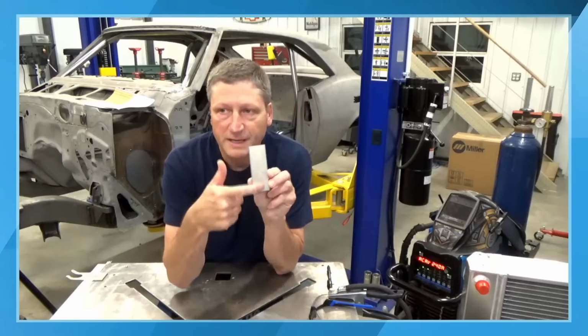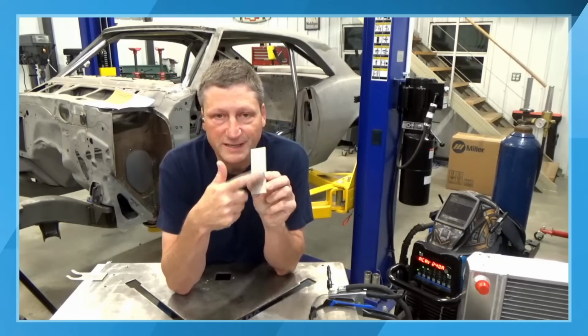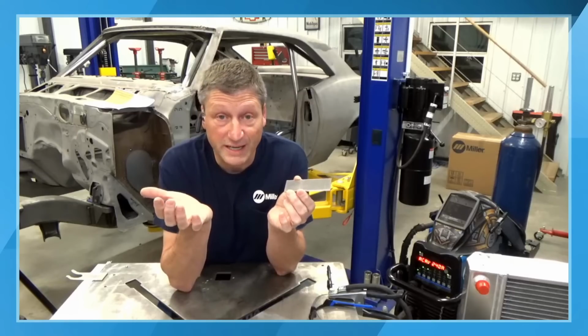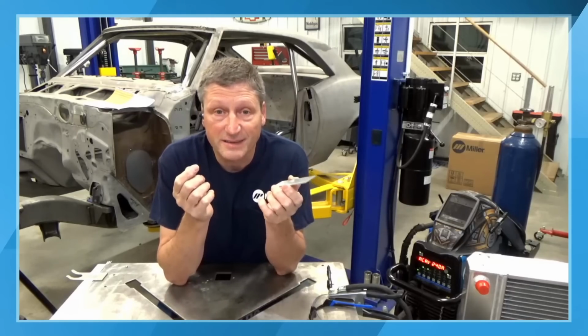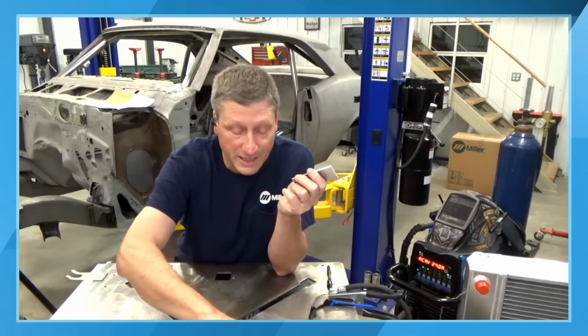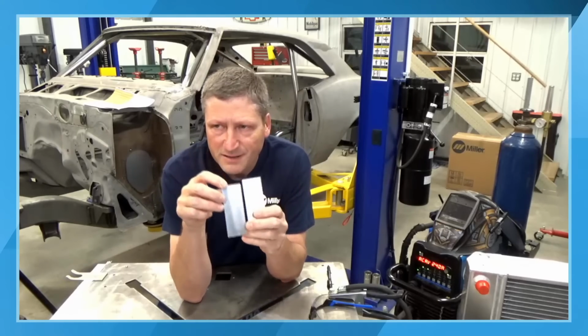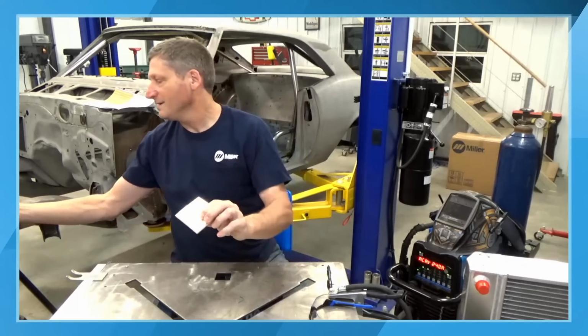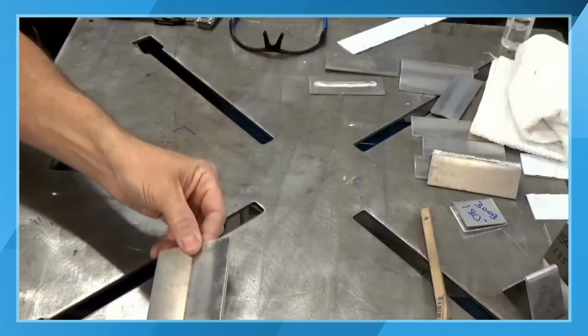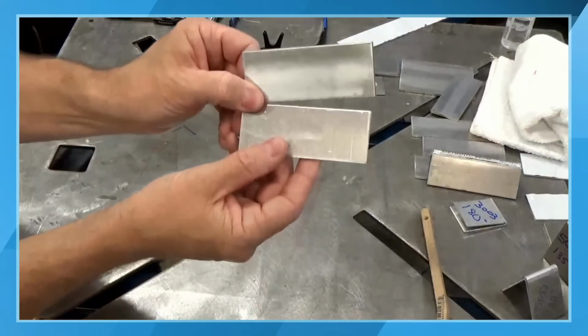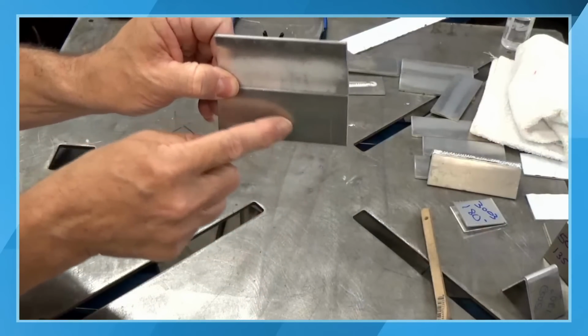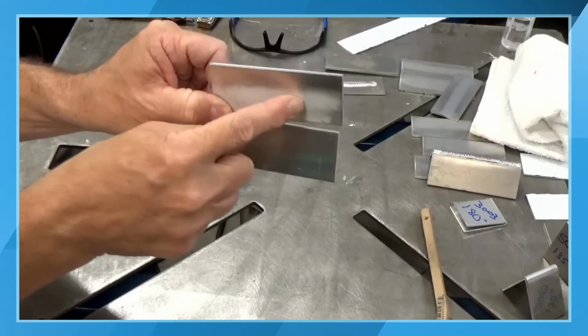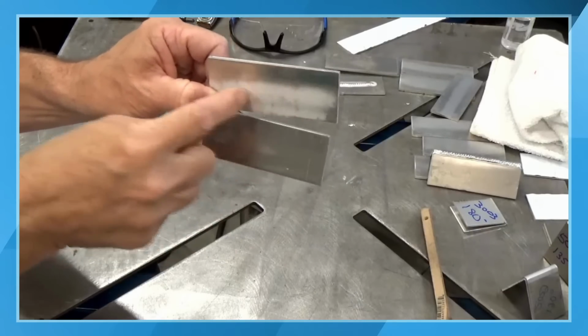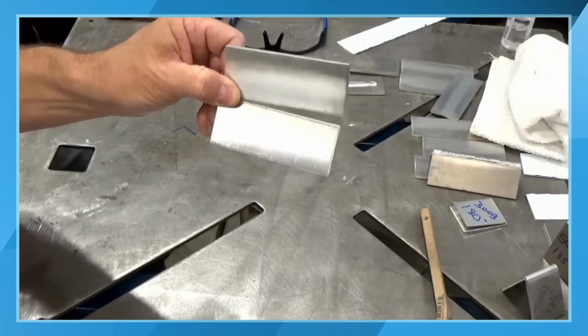So aluminum, it's nice and shiny. Well, what you're seeing is the oxide layer. The oxide layer is shiny. What's underneath, the raw aluminum, not so shiny. So if you brush it, you can see the difference between the piece of aluminum that has not been brushed and the piece that I brushed. So the aluminum underneath it is actually dull. So the oxide layer is shiny and that's really super hard.